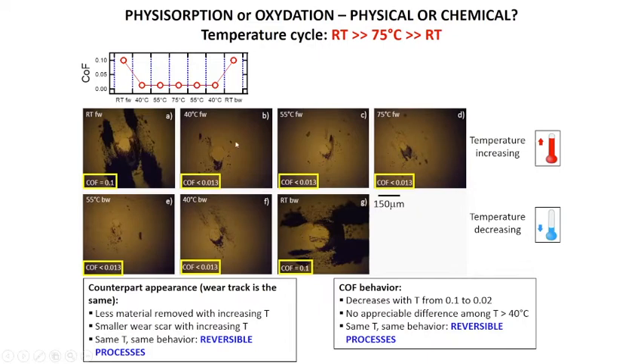The debris disappears as soon as we heat the substrate, so 40, 55, 75 degrees. And when you go back to room temperature, again we found this very big amount of debris. This means that the process of heating the substrate induces a reversible process. So still we are supporting the thesis of water phase absorption and not of oxidation of the coating.